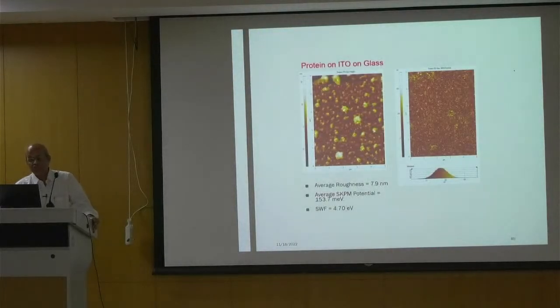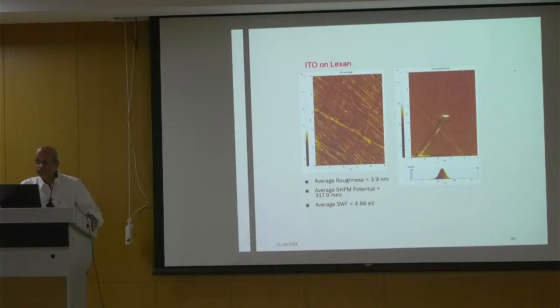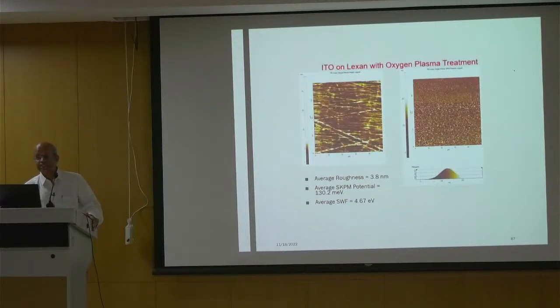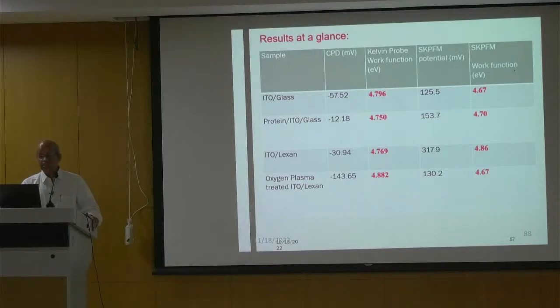So we got the pictures. I will show you the result. Yeah, these are the results. You see the first column is what the samples we have, ITO on a glass substrate. On the same sample we have put bovine serum albumin, and we have prepared ITO on Lexon under identical conditions, and we have treated the sample of ITO on Lexon with oxygen plasma for 35 minutes.